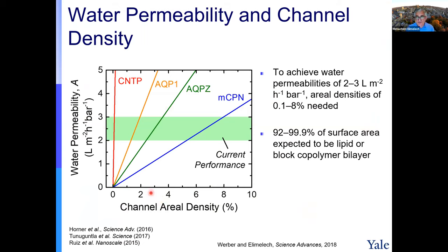So first we analyzed, we said, okay, we know the permeability of all of these channels, carbon nanotubes, porin, aquaporin, and synthetic channels. We know it from the literature. And we said, let's incorporate them into a membrane, theoretically. And we wanted to know what the areal coverage is, because these are highly permeable. What area of the membrane should be covered so we can get the permeability that we know is good for reverse osmosis, and there is no need to work at higher permeability, between 2 and 3 LMH per bar. And we see that it varies.